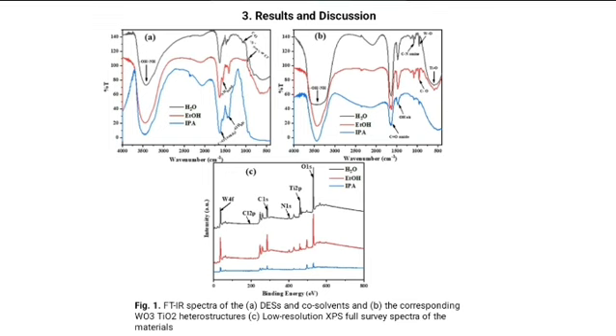So according to the FTIR spectra, the vibrational frequency of the pristine eutectic solvent displayed a characteristic broad OH and NH overlapping band at around 3423 to 3452 wave number, while the amide C double bond O band was at 1634 wave number. More also, the peak at 1554 wave number could be attributed to the NH band and was medium in the ethanol base DES and was very weak in the water and isopropyl base DES, which is a deep eutectic solvent.